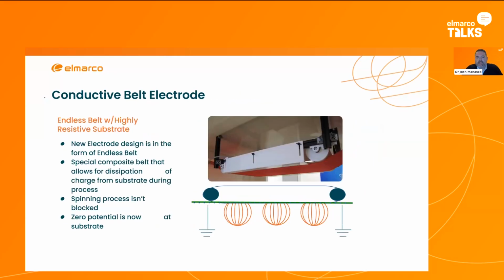We came up with this design for a conductive belt electrode. We call it endless belt because it's a loop. In this case, you have the substrate actually in contact with the collecting electrode. And it's a conductive belt, so that allows you to discharge the substrate continuously while you're spinning. You would still charge that belt with the opposite charge of what your spinning electrode's charged at.